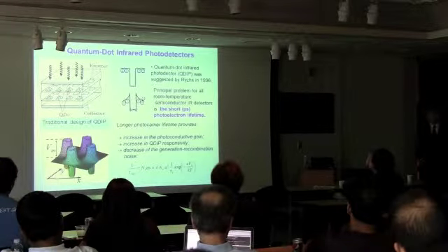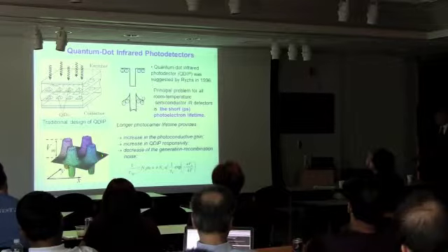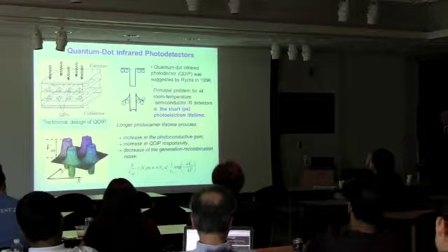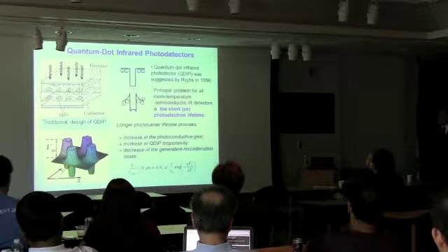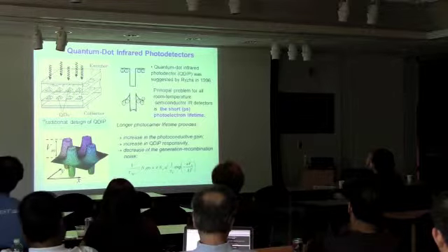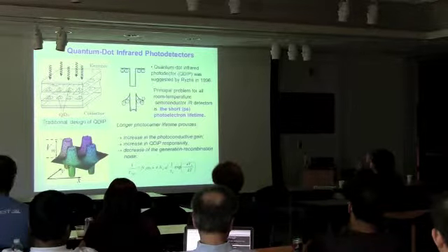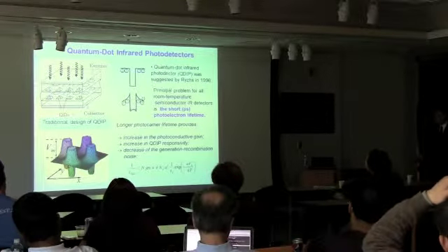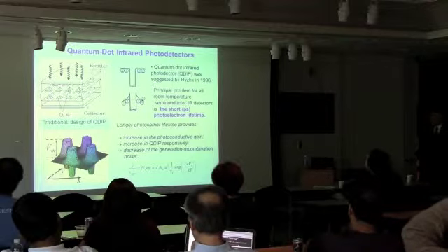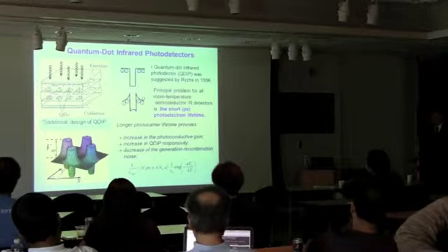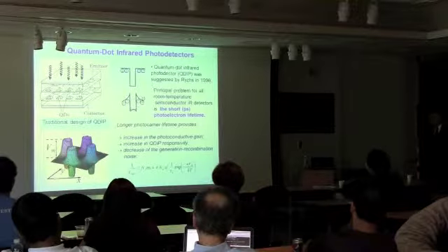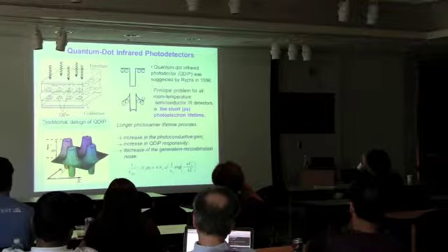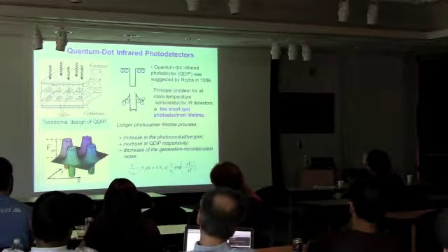the potential profile drawn here. If an electron is outside of the dot, then it needs energy to go back. Because as soon as I throw an electron out of the dot, it loses energy and moves between the dots, and it will be difficult for the dot to take the electron back. And so depending on the height of the potential barrier, the time of capturing in the dot back increases exponentially. So here its probability goes down exponentially, or lifetime really goes exponentially up with the increase of